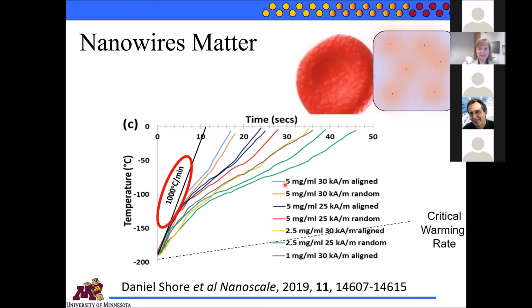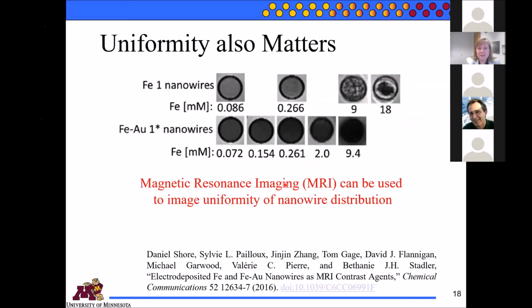So what else matters? It turns out uniformity matters. One way to check the uniformity in a vial, if there was a vessel, you would see that in here, is to use something like MRI. We actually looked at that a while ago with my colleagues Michael Garwood and Valerie Pierre. And we find that our nanowires are actually pretty good MRI contrast agents. So in this application, we might just want to check that this type of thing doesn't happen at the concentrations that we're interested in, so that we get uniform heating.